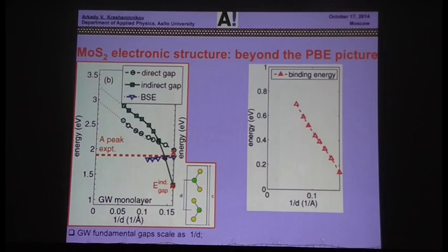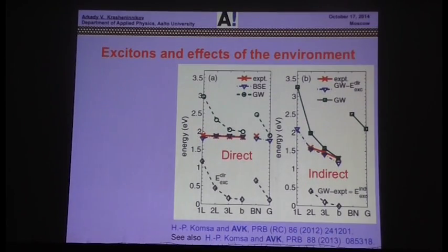But in fact, the situation is pretty simple. If you calculate exciton binding energy by solving numerically the Bethe-Salpeter equation, you will find that exciton binding energy also increases when you increase the separation between the layers. So this means that exciton binding energy is larger in 2D systems than in bulk materials. In bulk it's about 0.1 eV, in single layers about 1 eV. It's a very interesting effect, especially as it means that electron and hole wave functions overlap more in low-dimensional material. They basically are confined into a single layer.